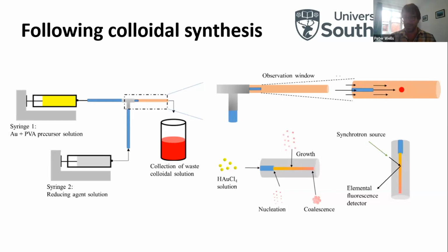You also need to make sure you add some fluorinated oil and some things to suppress hydrogen production. And George was fantastic in really being diligent in reducing the fouling, so we could be absolutely certain there was no fouling of the gold precursor on the wall of the Kapton tube that was our reactor. And we could then follow this at the beamline.